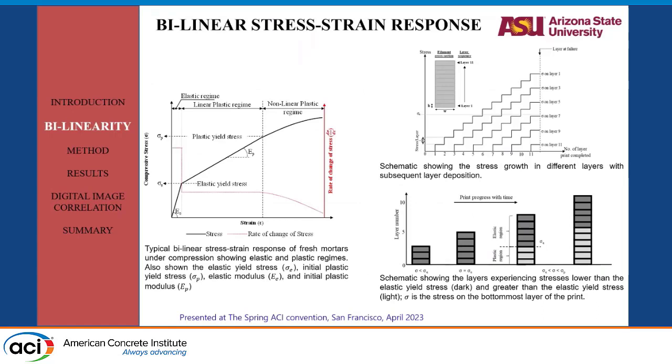What we did was cast some cylinders, as proper casting was required, and saw if the stress-strain graph showed an elastic response or not. We did see an elastic response in a very small strain range, and it was followed by a strain-hardening, plastic kind of response. Now, as the overall mechanical response itself changes, we need to develop a theoretical model to be able to predict numerically what the failure height is.